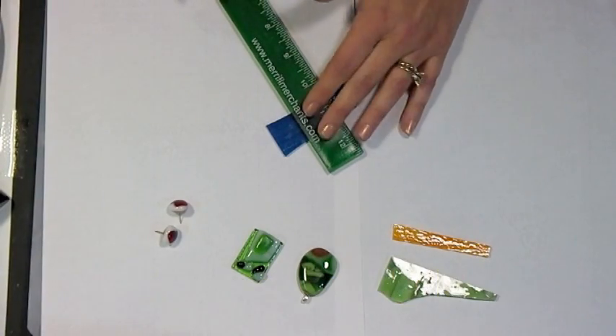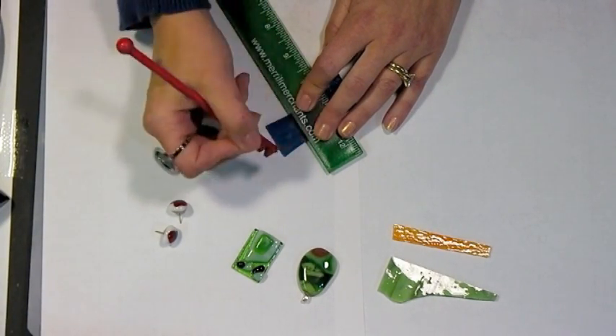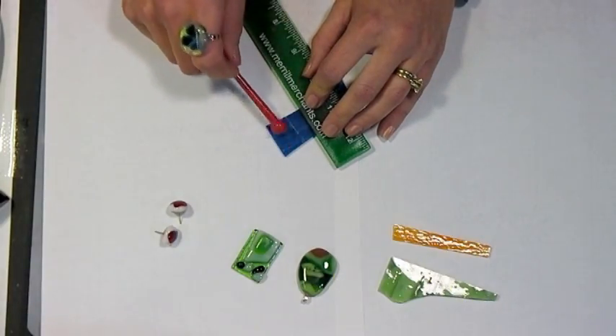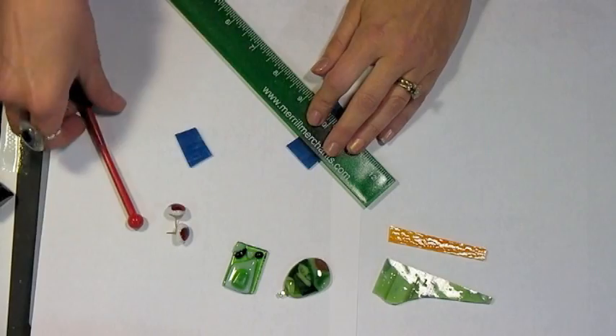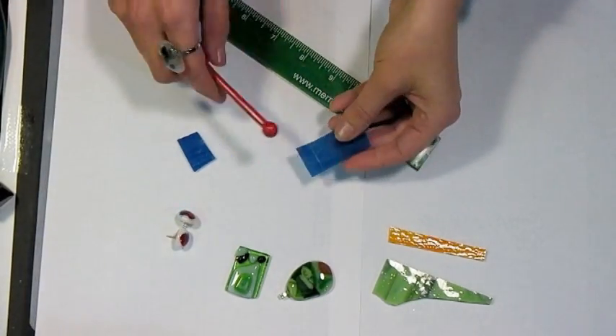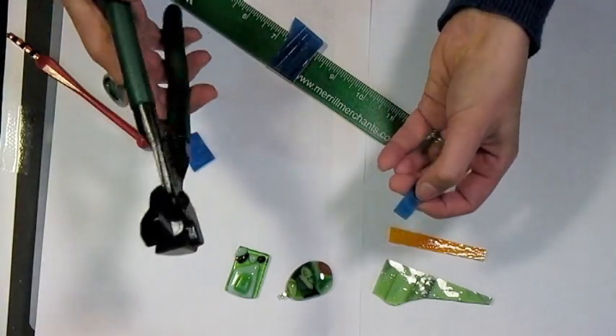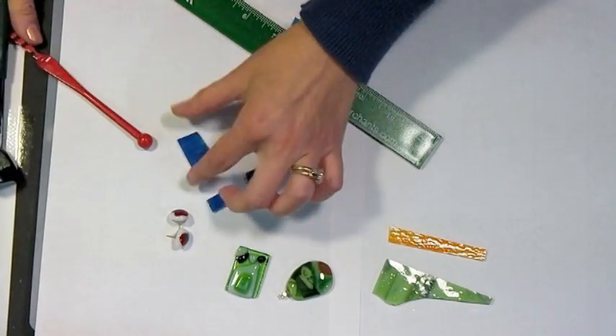I'm just going to eyeball it and make a pendant. You hold your glass cutter straight up and down. I like thick rulers because they give you something to bear against. You only want to make one cut across — you should hear a hissing sound. Then you tap it and snap it. Easy as pie. Now I'll cut the smaller pieces for the earrings. You can hold the cutter at an angle; it seems to work either way. Tap it, and if you can't snap it, put it on the edge of a table or ruler and press to snap. For cutting small pieces, you may want to use a tile nipper — hold it in the middle of your glass and give it a squeeze for a nice clean cut.